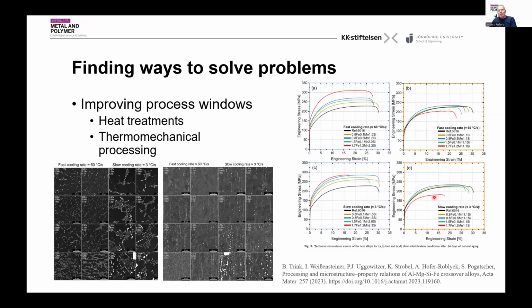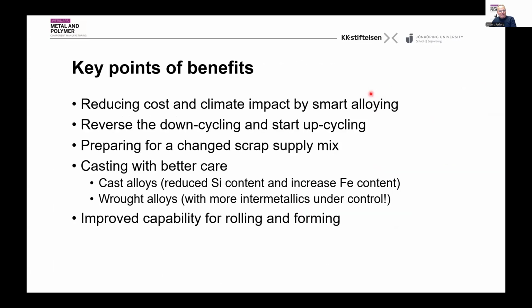reduction in properties. But if you go to the upper left, where you have a fast cooling, you actually get a decent performance even with a high iron content. So that means that understanding the effect of your processing conditions becomes very, very important in order to be able to produce good materials with both high strength and good elongation. So this is really something where we need to work more and understand this better in order to predict how the microstructures are formed and how they change during our processing. So we can go to the next.